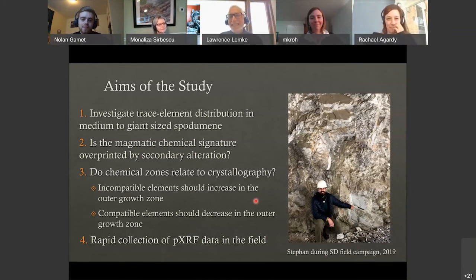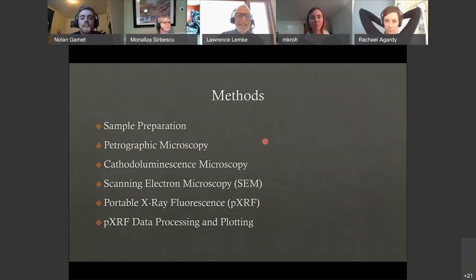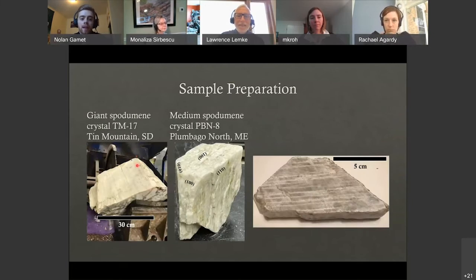The methods I included were sample preparation, petrographic microscopy, CL, SEM, PXRF, and the data processing and plotting. For the sample preparation, I began with slabbing the crystals perpendicular to their c-axis. This is an example of the giant spodumene crystal from Tin Mountain that is roughly 30 centimeters in diameter. This is the medium spodumene crystal from Plumbago North Pegmatite. After slabbing the crystals, I crystallographically oriented them based on cleavage planes and growth faces. Following that, I thoroughly washed and rinsed the samples to rid them of any saw marks, trace elements, contaminants, etc.